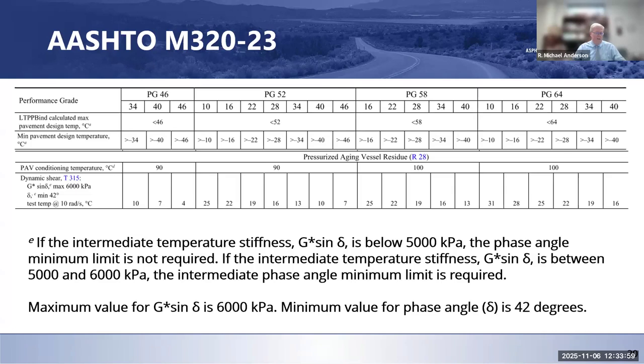But because we couldn't lower the variability through changing test conditions, it seemed appropriate. Well, how do you adjust it then to maybe account for the fact that you've got a binder which has a little high stiffness, but its phase angle is still pretty good, indicating that you've got good performance and what should be better relaxation. And that's what led to this proposed change that ultimately got adopted in AASHTO M 320, the 2023 version. So let's go to NCHRP report 673.